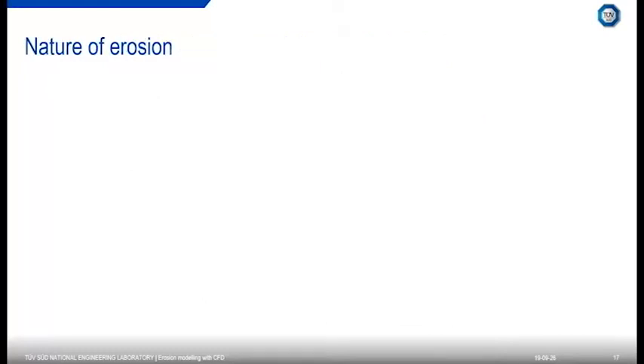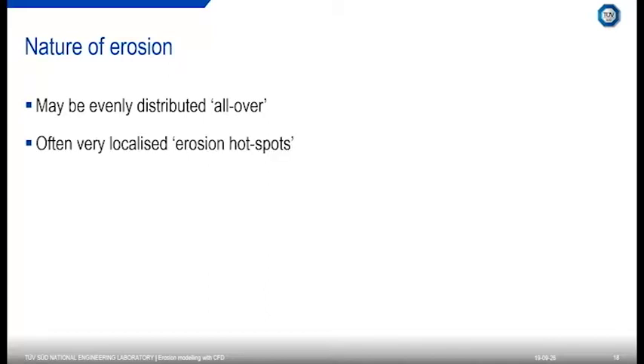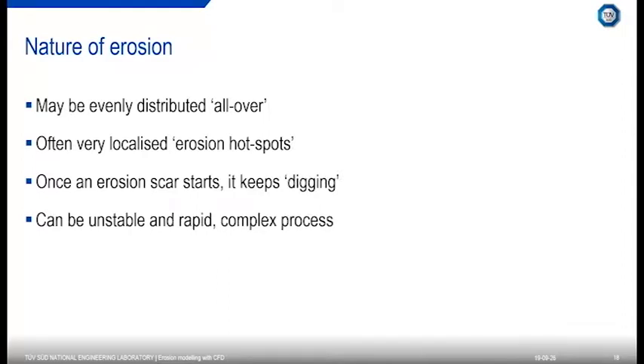So the nature of erosion, unfortunately, that's not simple either. It may be evenly distributed all over. It may be localized in erosion hotspots. Typically once an erosion scar starts, it keeps digging, but it may not keep on digging at the same rate, as the impact angle will change as it starts eroding. It can sometimes be very unstable, it can be rapid, and again, it's complex. And as I've reiterated a few times, it's not very well managed or understood.